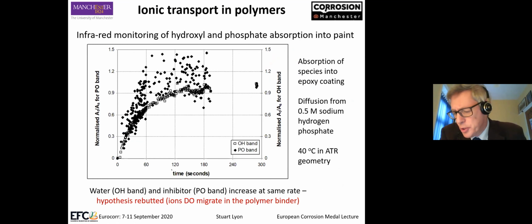So we used infrared monitoring of hydroxyl bands and phosphate bands into paint from half molar sodium hydrogen phosphate at 40 degrees C in an ATR, attenuated total reflection, geometry. We can see the water band is very steady, not a lovely Fickian diffusion. And the phosphate band is much more noisy because there's much less of a signal there to take, but we can see very clearly that the phosphate diffuses in at the same rate as the water. So they increase at the same rate, so the hypothesis is rebutted. Ions, or in this particular case phosphate, do migrate in epoxy binders.